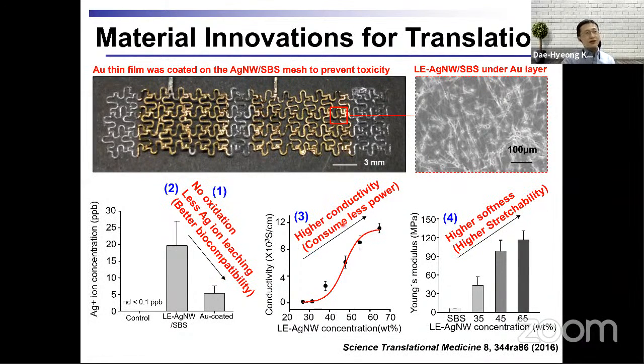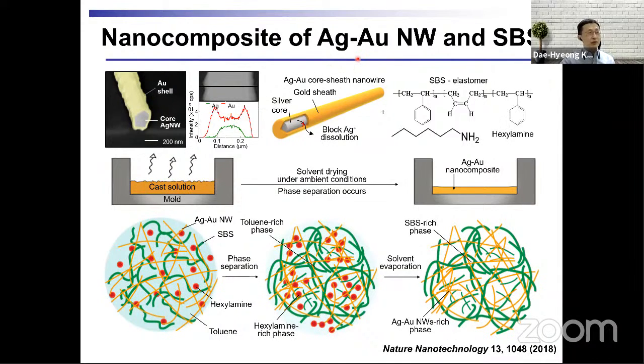We also wanted to have higher conductivity, and the easiest way to achieve higher conductivity is to put more nanowires into the composite. But as we add more nanowires, the composite will lose the intrinsic rubber-like property. Rather, it will become stiff and can be broken easily. So there is a trade-off between the conductivity and the softness, although we have to improve both. So to solve these issues, we replaced the silver nanowire with a core-shell type nanowire. We stick with the ultra-long silver nanowire because it provides a very high conductivity and low percolation threshold.